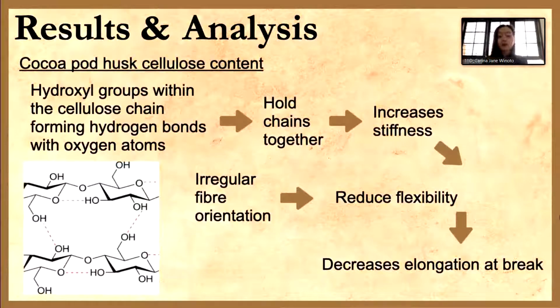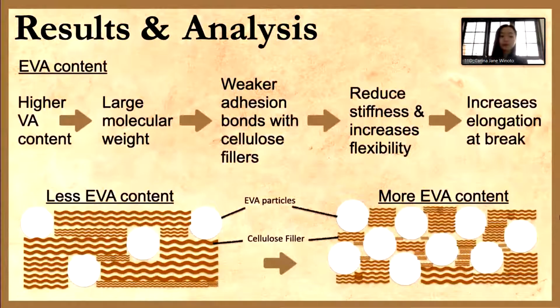Cocoa pod husk cellulose content causes hydroxyl groups within its cellulose chain to hold chains together once more using hydrogen bonds with oxygen atoms, increasing stiffness. However, contrastingly, after the optimum point, irregular fiber orientation also reduces flexibility, thus showing that increased cocoa pod husk cellulose content decreases elongation as a whole. However, for EVA, higher vinyl acetate with its large molecular weight causes weaker adhesion bonds to occur with cellulose fillers, reducing stiffness yet increasing flexibility, thus increasing its elongation at break.